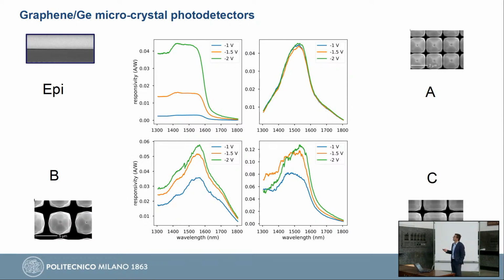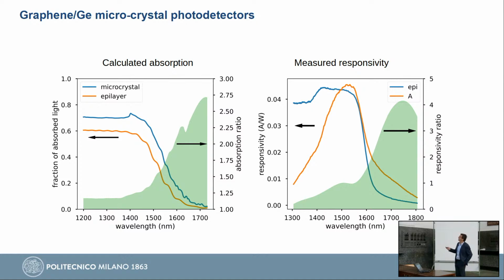So now we can make measurements, and we can compare with the flat device obtained exactly in the same way, also with graphene, and different morphologies. If we compare all this together, this was the calculated absorption that I was showing you before, where we expect an enhancement of the absorption. And these are the real data, the responsivity data. And again, we see a stronger absorption in the infrared, where we want it. So we can actually extend the sensitivity of our device by engineering the coupling between the incoming light and the absorbing medium, in our case germanium.